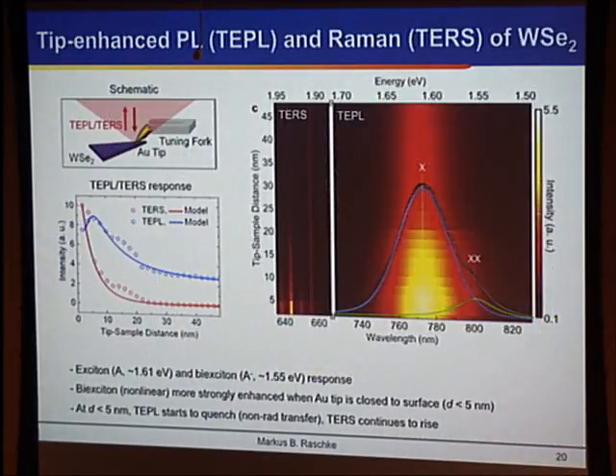And so what we do is use the near-field tip-sample interaction, and not only to look at the exciton emission. Here you see the exciton emergence and enhancement as we approach the tip within the last few nanometers. This is what I mentioned to you, where we get this onset of the near-field interaction at about 10 nanometers, and then you see this bright emergence of the exciton. You see a little bit of the bi-exciton, but simultaneously with the exciton, we can look at the Raman emission as a probe for the lattice structure, and then from changes in the peak position of the Raman emission, you can correlate whether the exciton enhancement or quenching is associated with changes in the lattice.